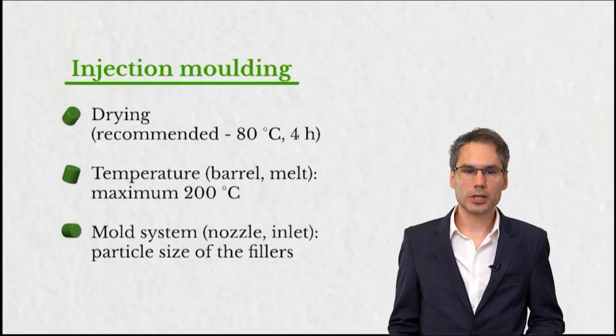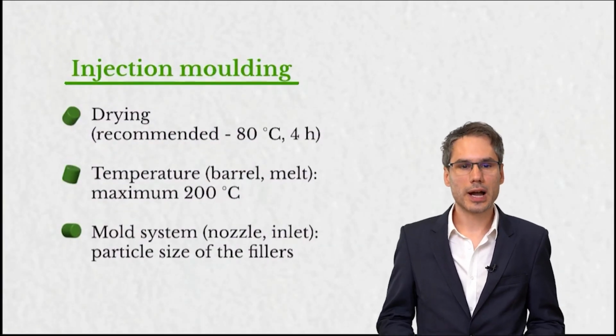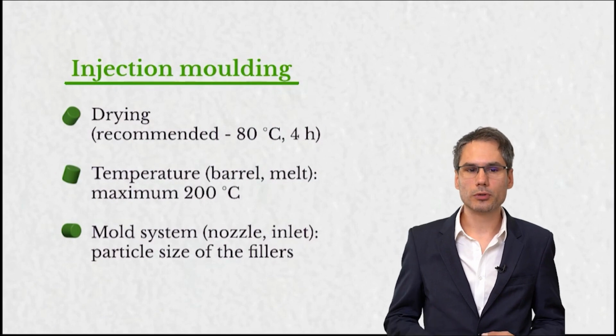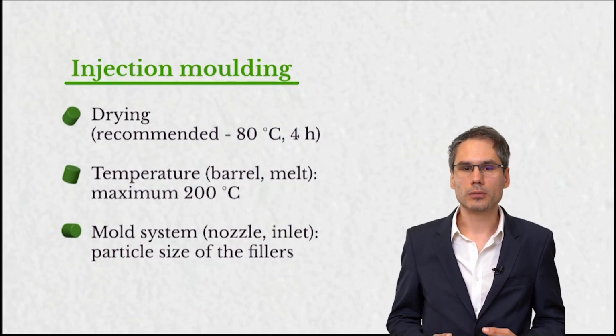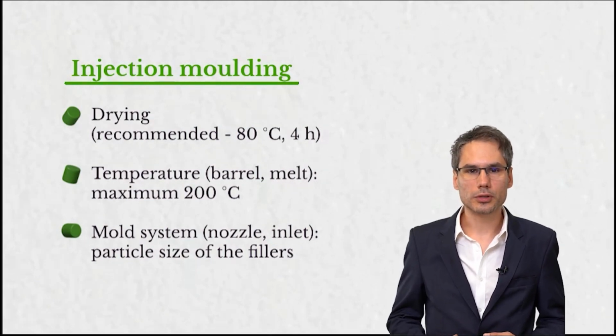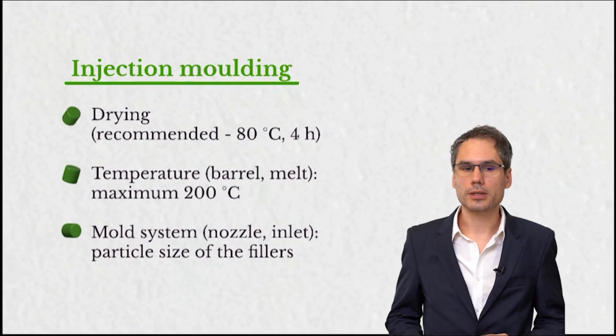Few words about the injection molding of the biogrades. Drying is very important in case of moisture-sensitive material like this. Higher temperatures can cause burnout. That's why this is the maximum 200 degrees, which we propose for the processing.